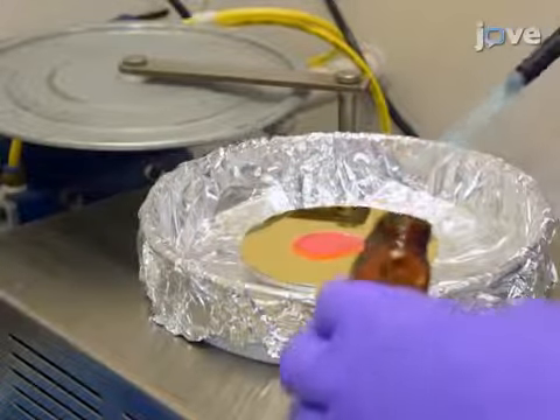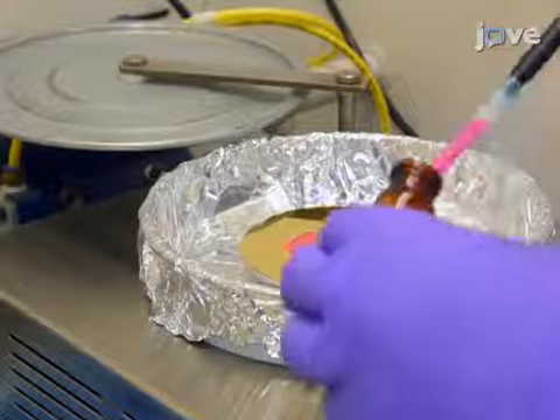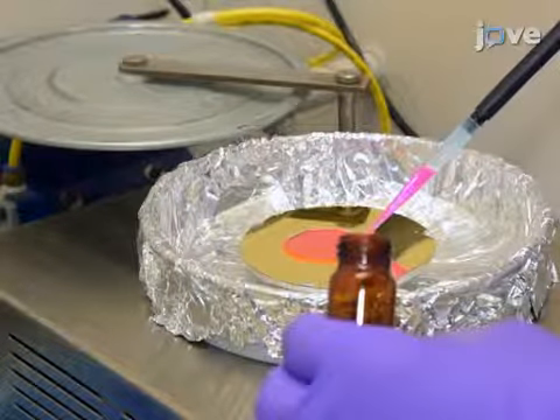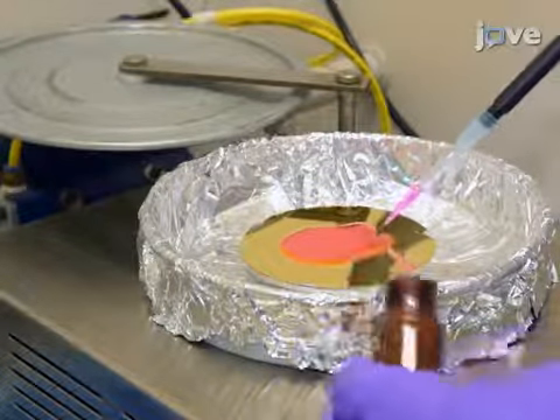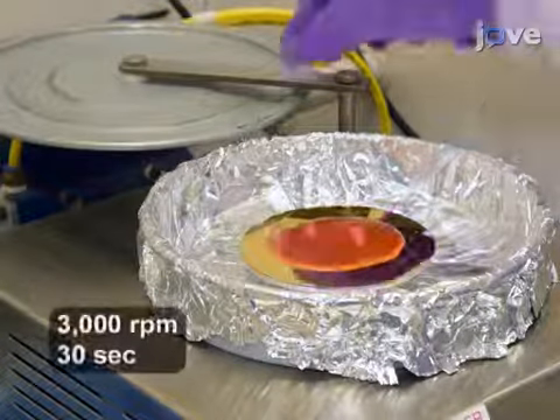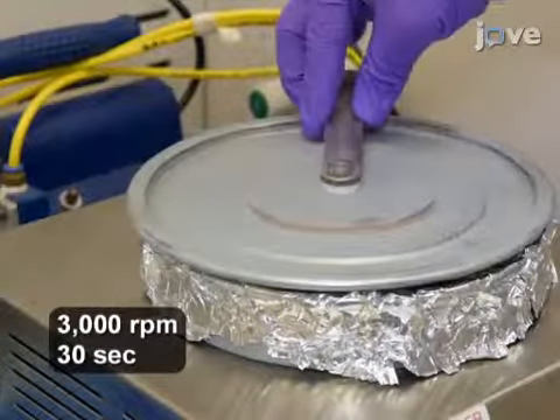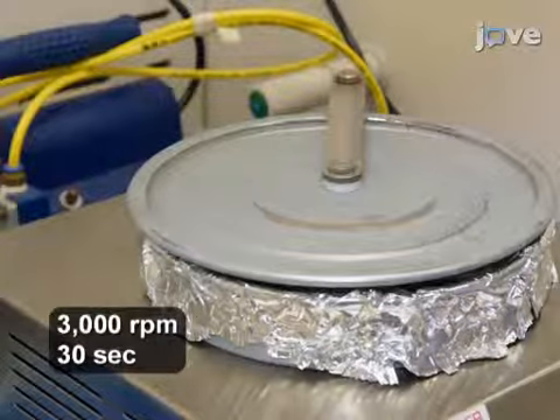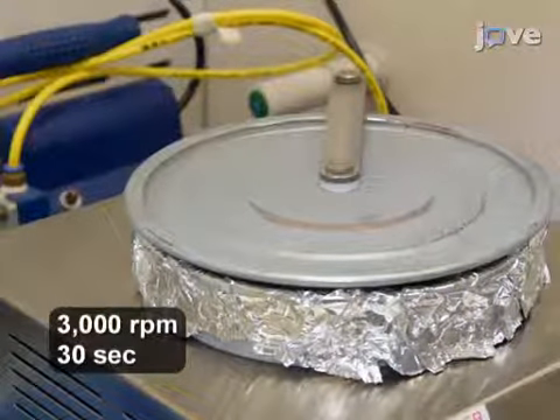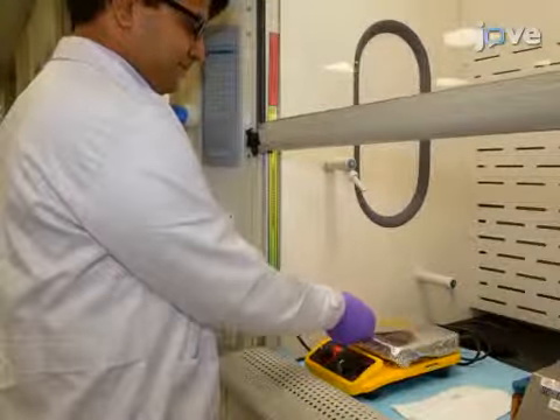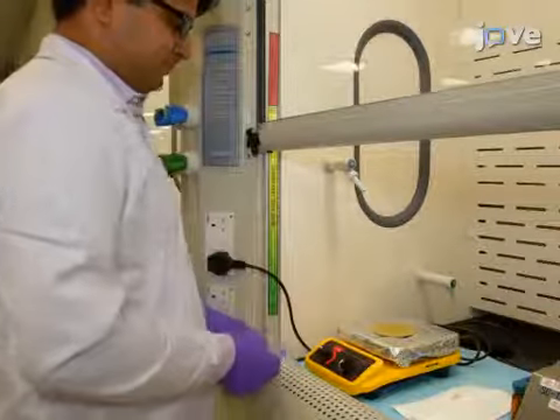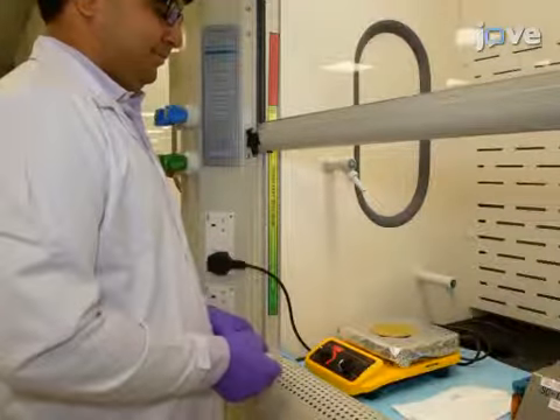When finished in the E-beam evaporator, place the wafer into a spin coater setup and add 5 milliliters of a photoresist to the center of the wafer. Spin the wafer at 3000 RPMs for 30 seconds to produce a 2 micrometer thick photoresist layer. Next, pre-bake the photoresist on a hot plate at 100 degrees Celsius for 1.5 minutes.